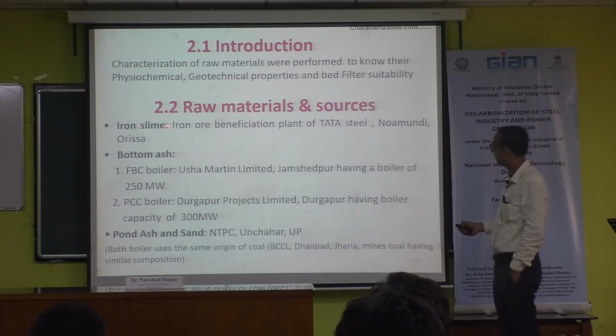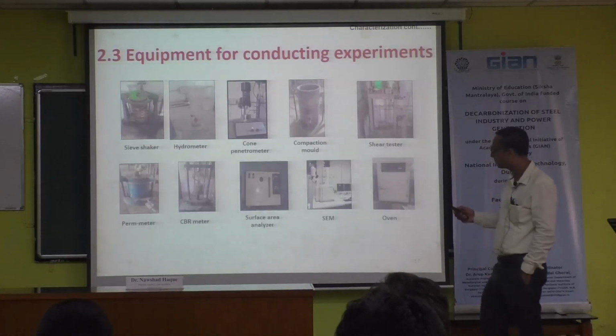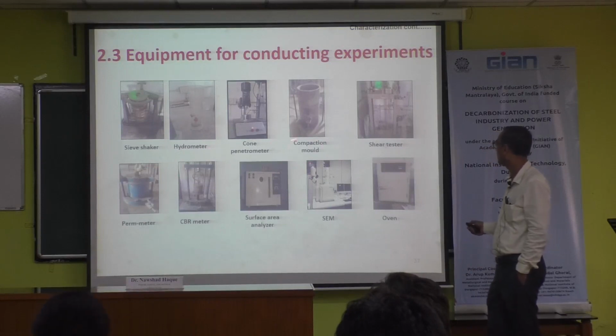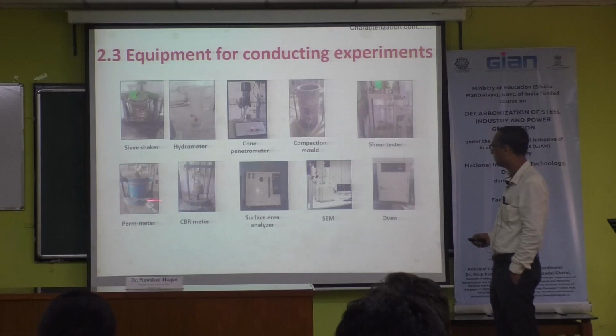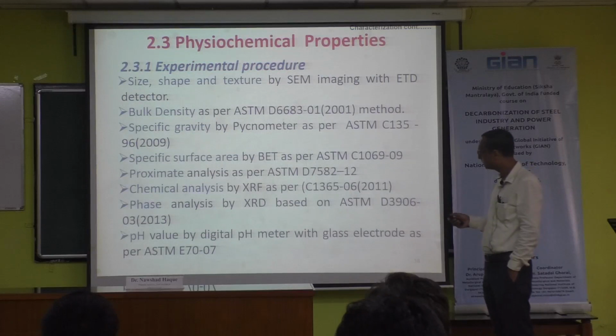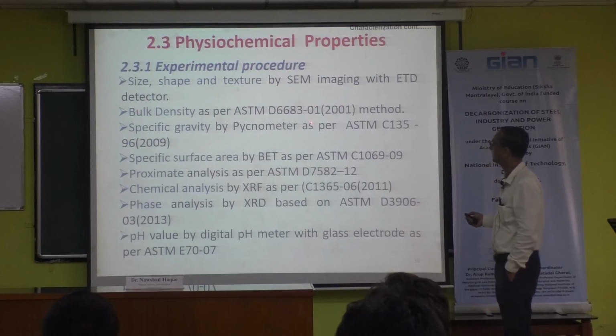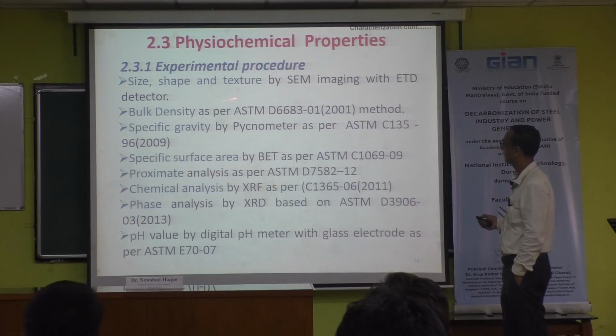So we have taken the raw materials: iron ore slime, bottom ash from FBC and PCC, and fly ash collected from the ATPC filter. The different tests we have done are sieve analysis, hydrometer, density, cone penetrometer, compaction test, CBR test, permeability test, surface area. We have done different experiments as per the ASTM standard: size, shape, texture, bulk density, specific gravity, specific surface area, chemical analysis, phase analysis, pH.